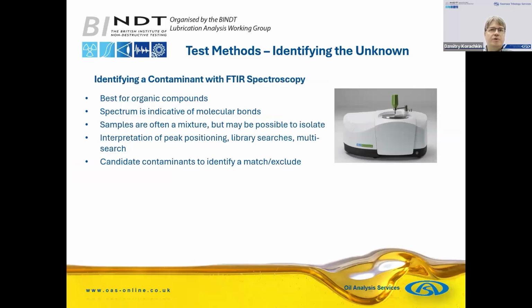Another useful method is infrared spectroscopy. This works best for organic compounds. The spectrum that's produced is indicative of molecular bonds present in the sample. When samples are a mixture, it may be possible to isolate the samples and test each component individually. But we also have access to previously tested samples, library spectra, and can not only identify a contaminant, but we may be able to exclude certain contaminants.